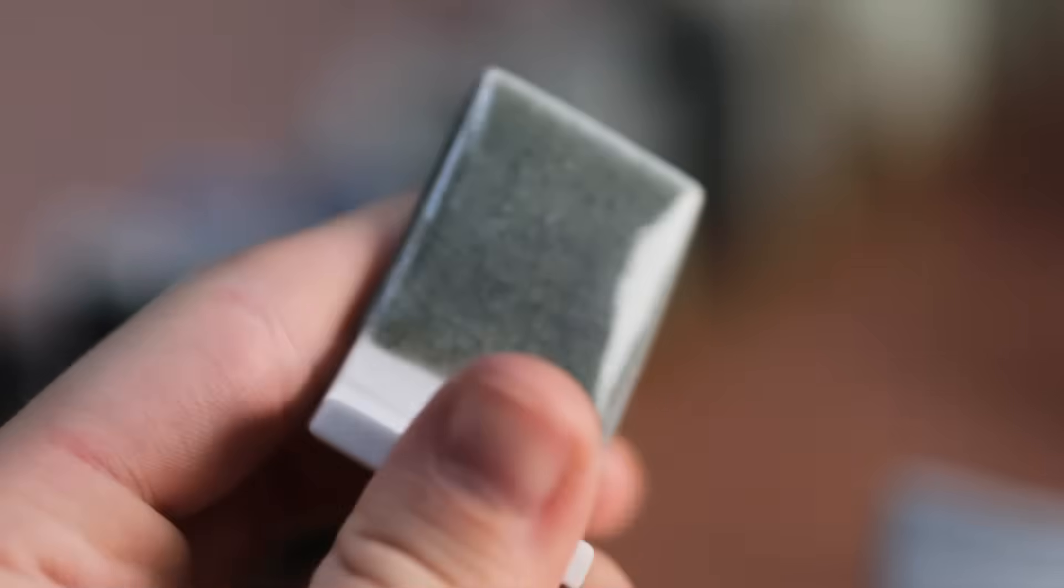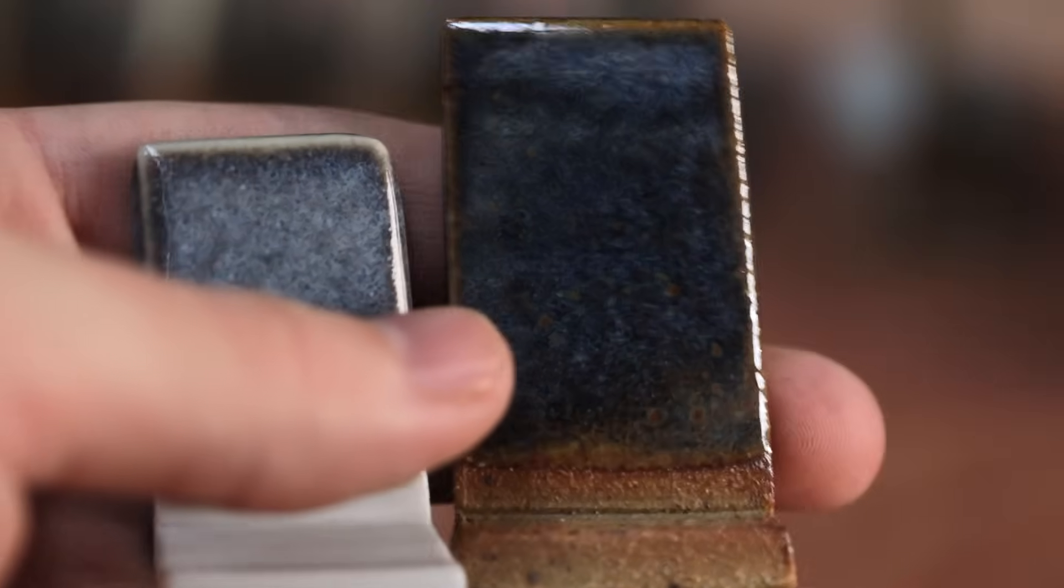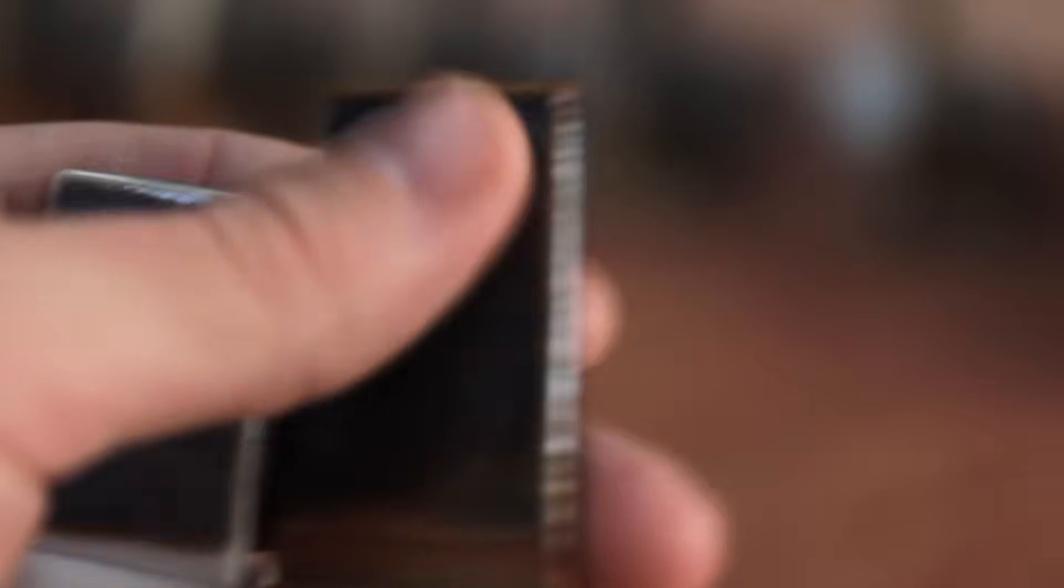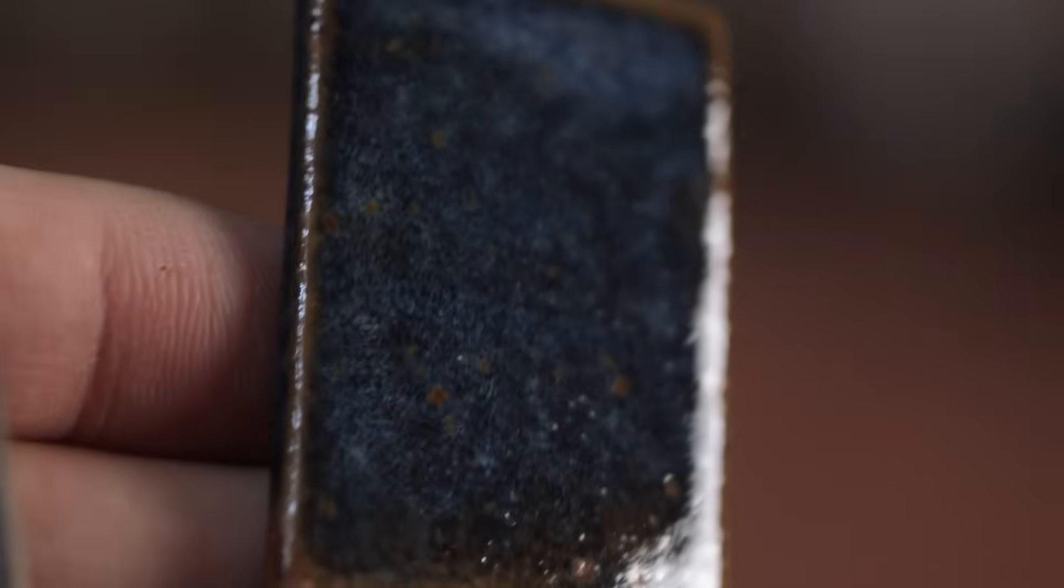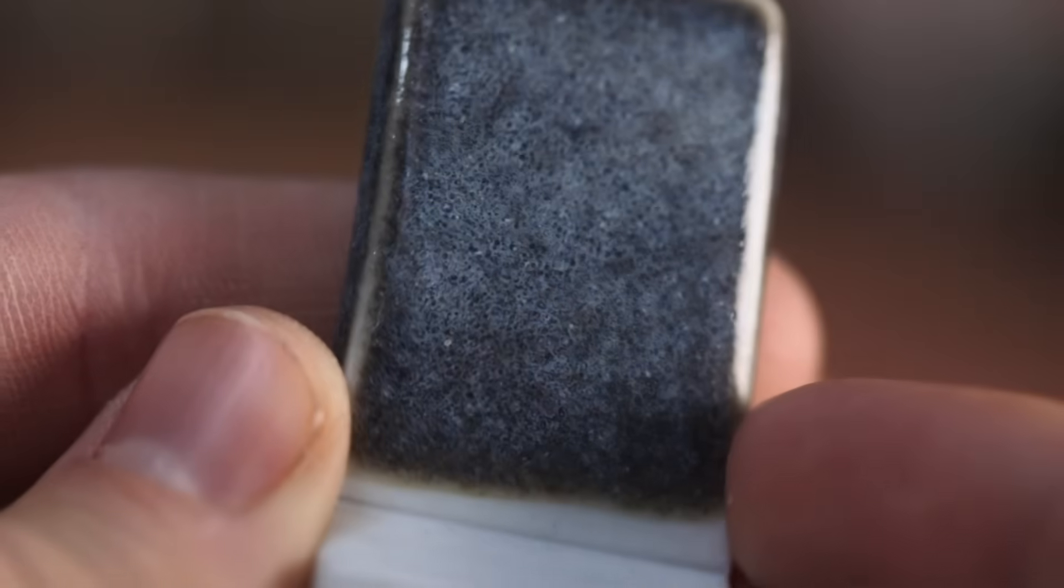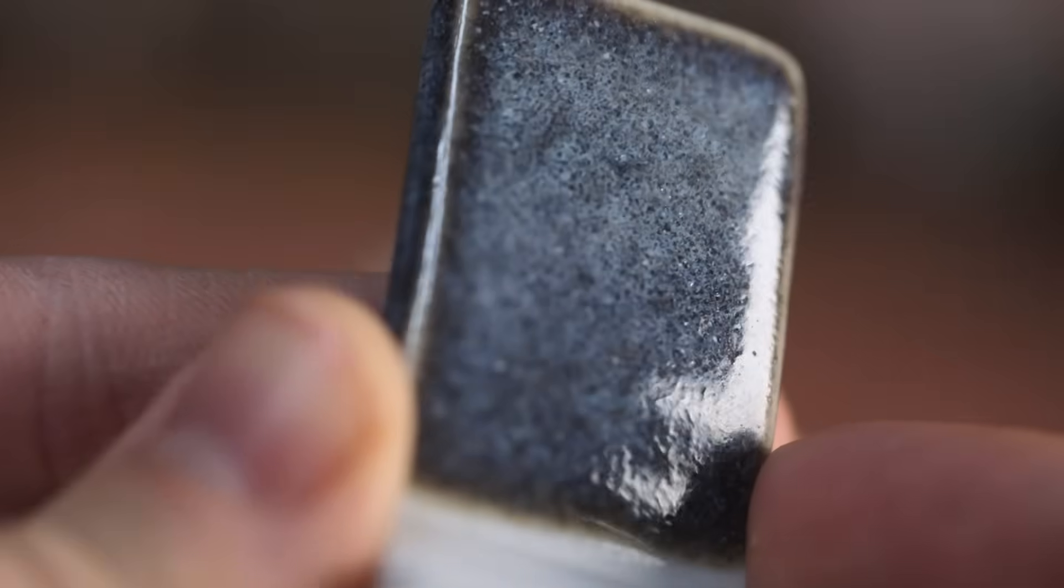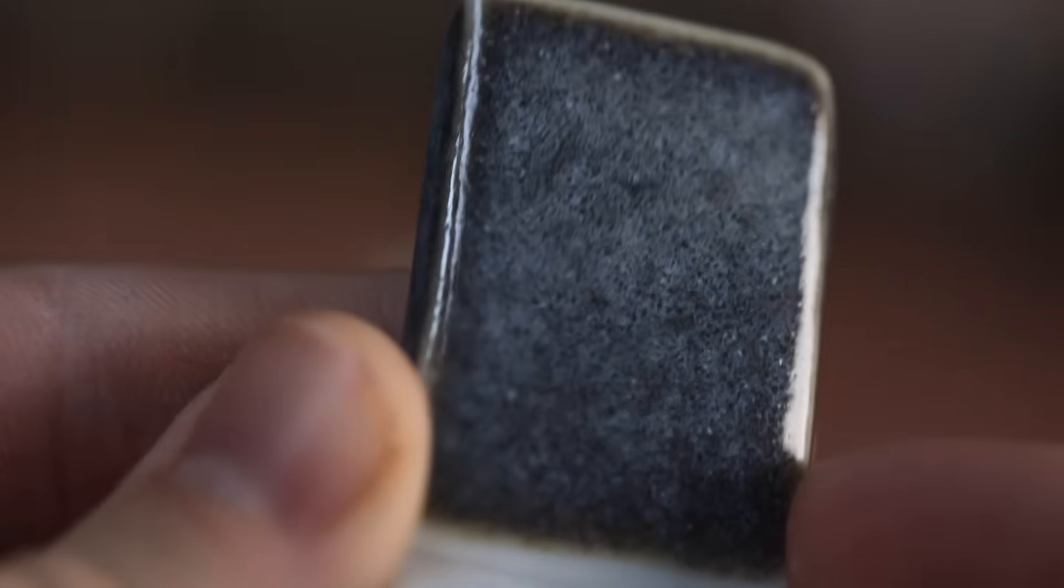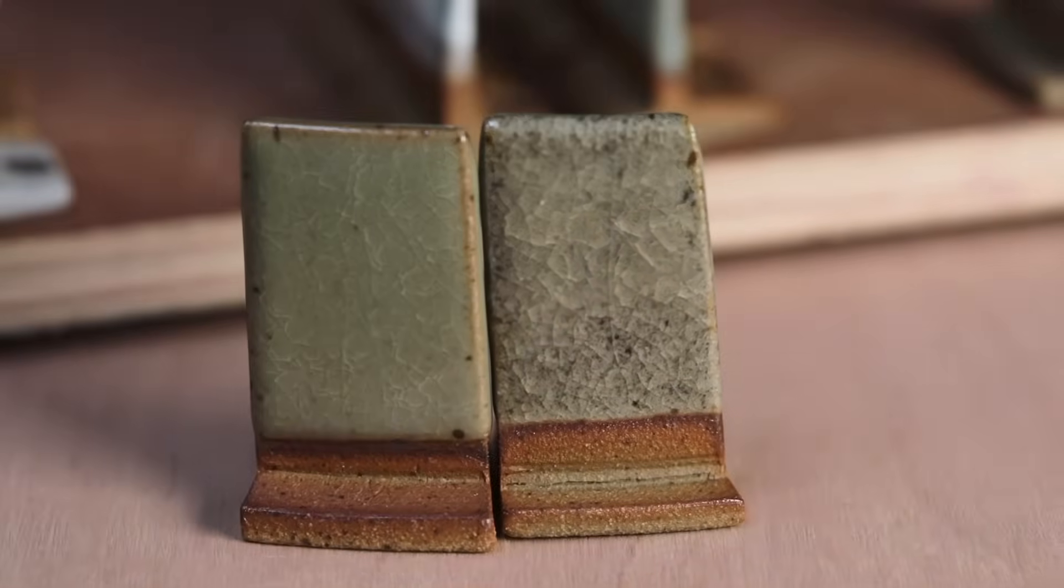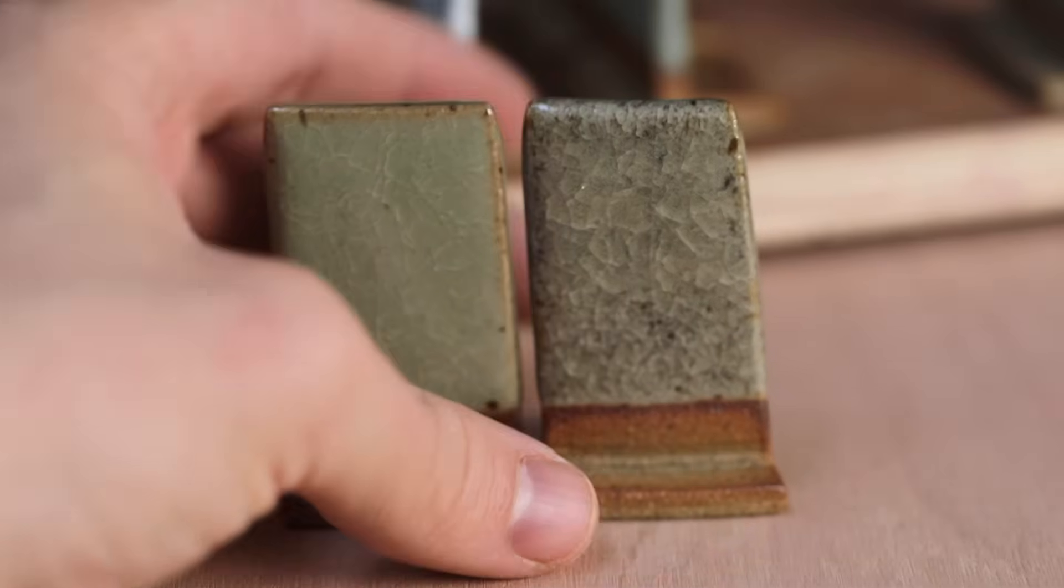Perhaps the strangest crackle alternative was this one, which again is just the base glaze, but this time with the addition of 4% rutile, which changes both texture and colour considerably. Rutile contains titanium dioxide, and generally another mix of minerals, and it tends to affect the texture more so than anything else, creating these tiny streaks and a sort of mottled effect across the glaze's surface. In subsequent tests, I combined rutile with a lot of iron, but in doing so I ended up creating glazes that were incredibly fluid, and simply ran all over the test tiles and the kiln shelf. Here are two more. On the right is the crackle, but with 1% rutile, and on the left is the base, but with 0.5% chrome oxide, both of which I really dislike, and I won't be using.